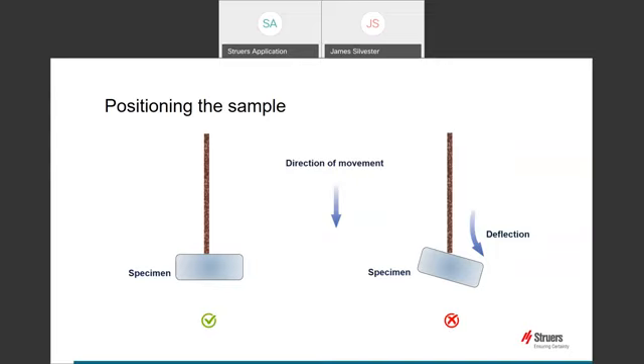Cutting too fast can also give this issue, with the wheel trying to find the easiest way through a sample, which can cause the wheel to wander. Again, this will either lead to wheel failure or cutting into the T-slot bed. If there is no other option but to cut on an angled surface, our advice is to start very slowly and allow the abrasive to cut a small notch in the surface to act as a path which should allow the wheel to follow during the rest of the cut.